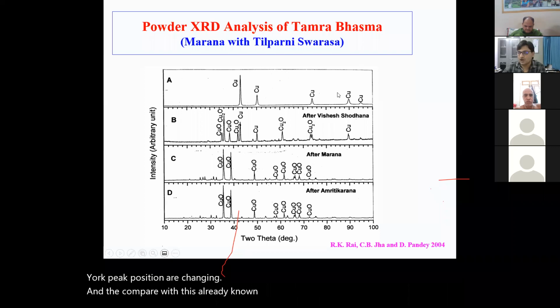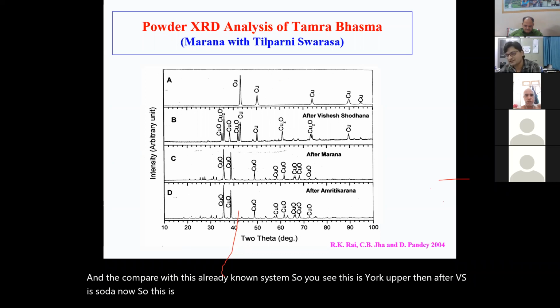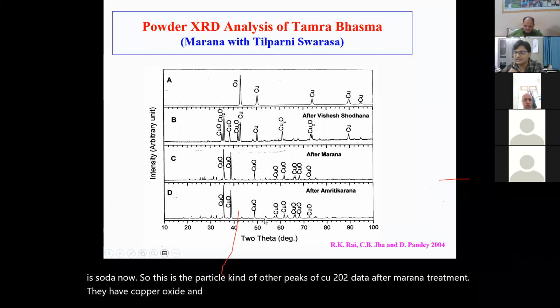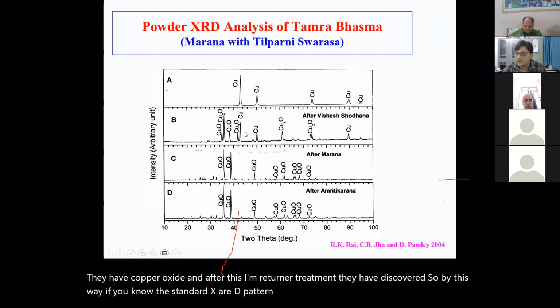So you see, this is your copper. Then after Vishesh Shodhana, so this is a particular kind of treatment which Ayurveda doctors are doing. So after that you see you have other peaks of Cu2O. So how do they know this peak is related with Cu2O? They know from the standard ICDD data. Now you see after Marana treatment they have copper oxide, and after this Amritikarana treatment they have this. So in this way, if you know the standard XRD pattern, you can identify the phases present in your material.